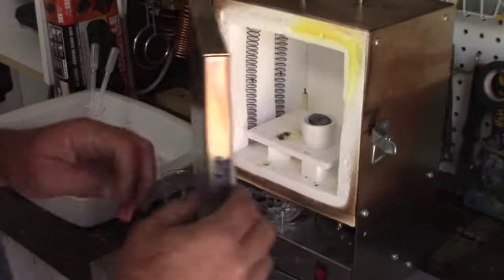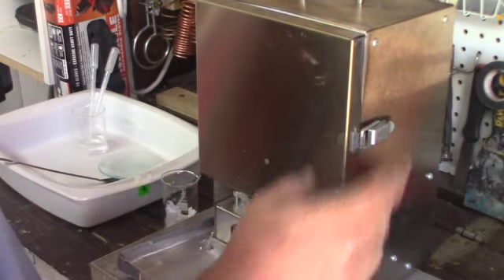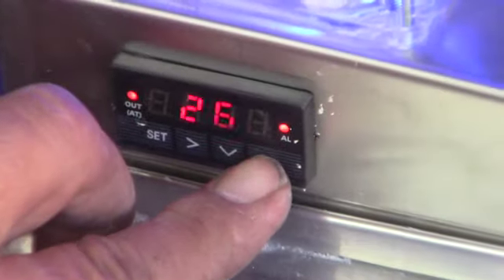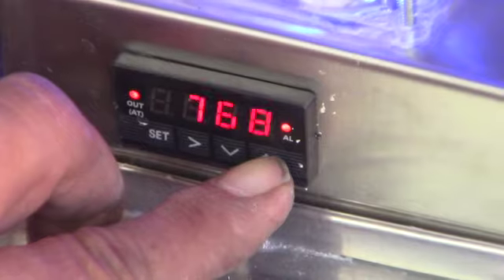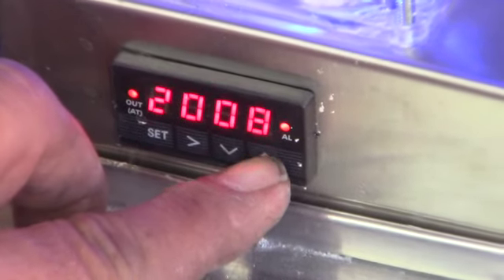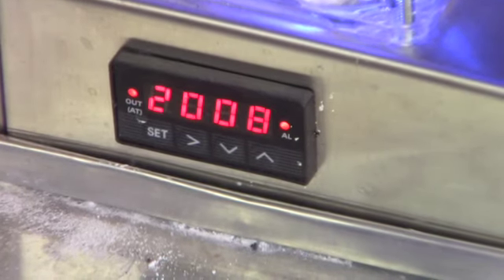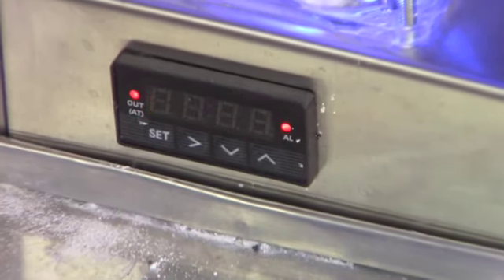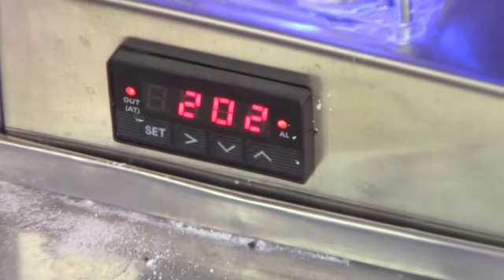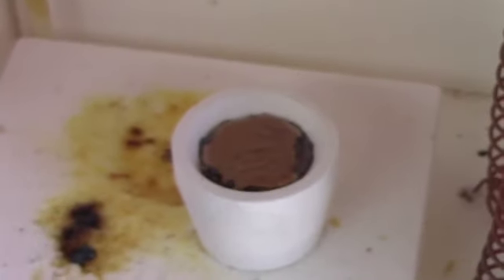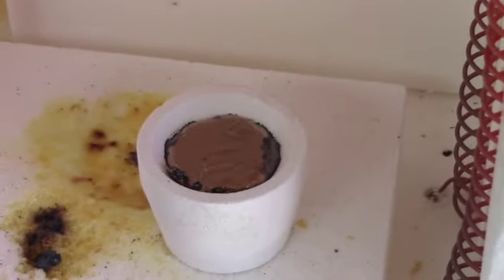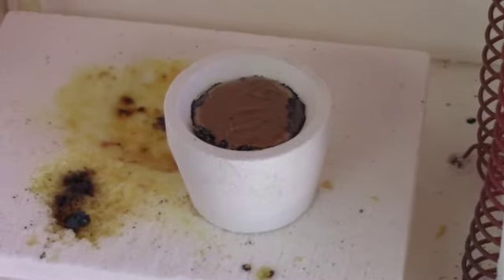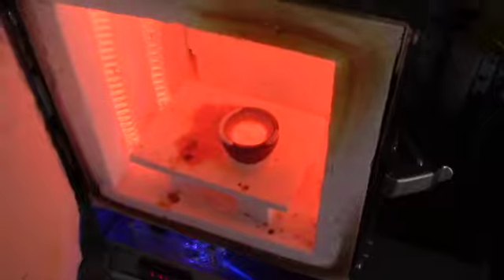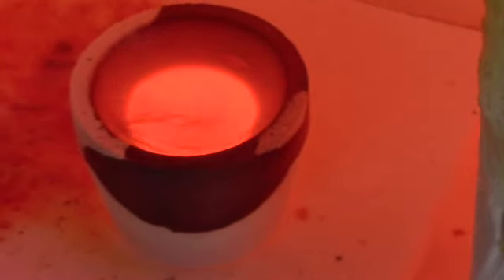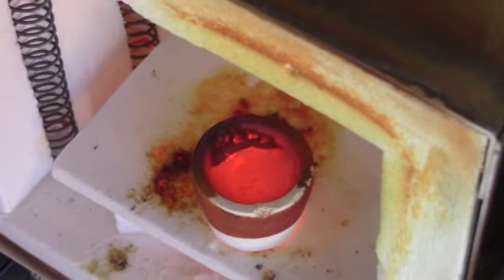This is what we have before we start cooking it. And we'll run the temperature up. And start cooking. So once we've gotten up the temperature, the lead's melted. So here you just see melted lead. It's still a bit shiny on the top. Once it gets to the oxidation state, you'll see fumes coming off, and you'll get a haze that will form over the top of the lead. That's lead oxide. Then it will immediately absorb into the coupelle.